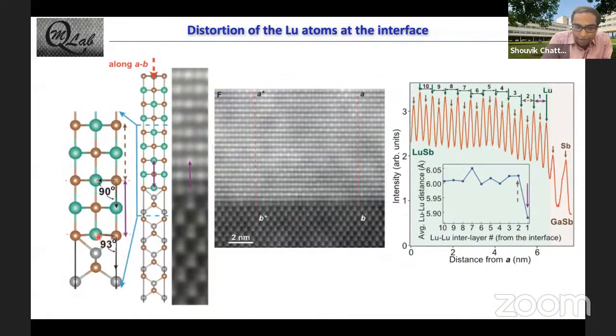So what that translates to is that if you were able to calculate the interatomic distance along this column, the first interatomic distance between the lutetium atoms will be a little smaller than the rest of them. And this we can actually directly calculate from the TEM measurements on our thin films, and this is experimental data. What we do here is that we go along these columns, and just for statistics, we do an average over all these different columns going from here to here. And this is what is plotted here. Then we can calculate this lutetium interatomic distance, 1, 2, 3, 4. 1 is the first lutetium atomic distance near the interface. Here is the interface. And what we find is indeed that the first lutetium interatomic distance is slightly shorter than the rest of them.